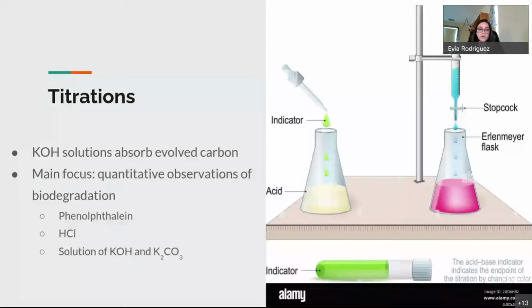So the carbon dioxide will find its way into the potassium hydroxide solution because the jar is a closed environment. It's sealed and there's no air getting in. So once that carbon dioxide finds its way into the potassium hydroxide solution, the potassium hydroxide becomes a mixture of potassium hydroxide and potassium carbonate of an unknown concentration. So I used hydrochloric acid and phenolphthalein to titrate the solution and figure out how much of the solution was potassium hydroxide and how much was potassium carbonate.